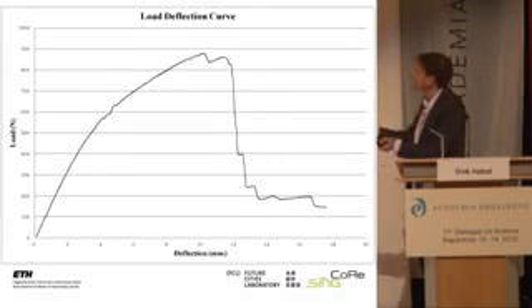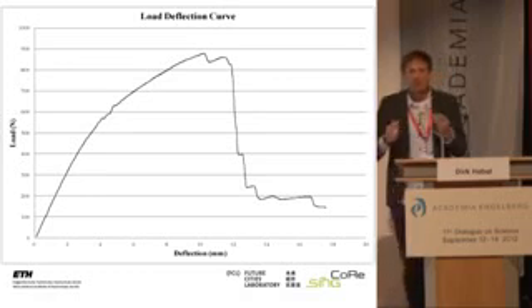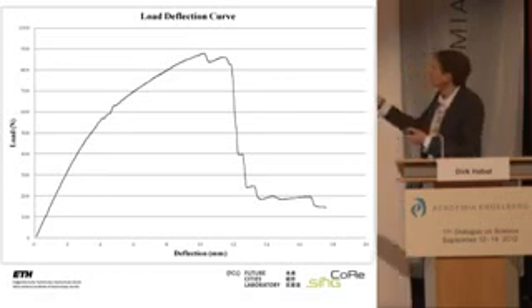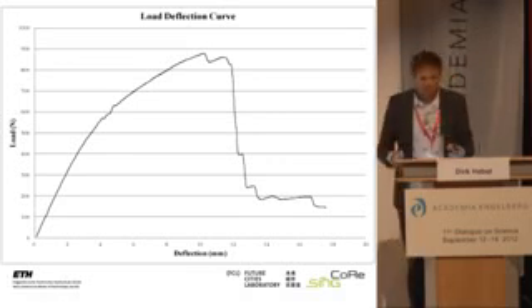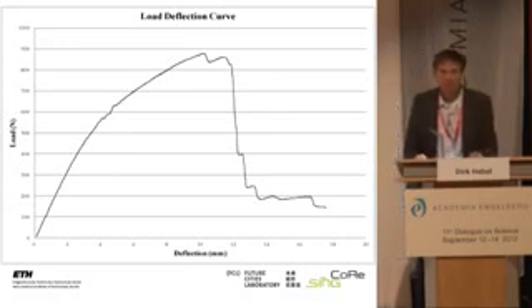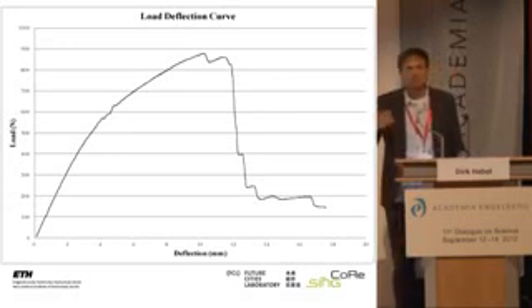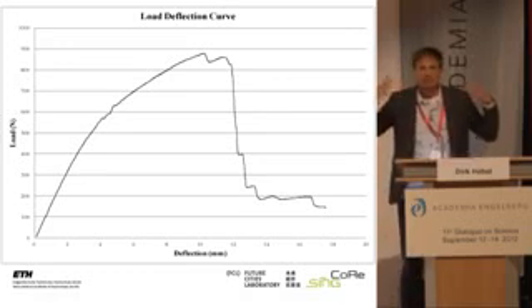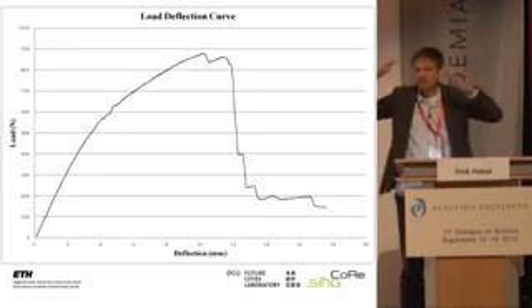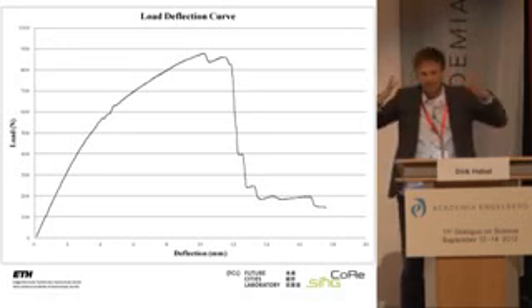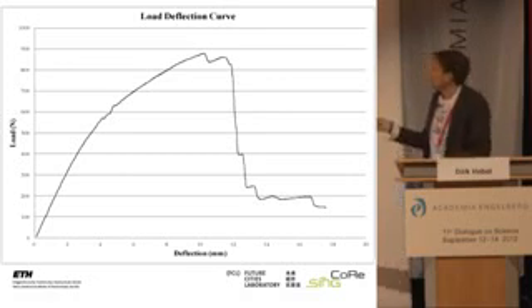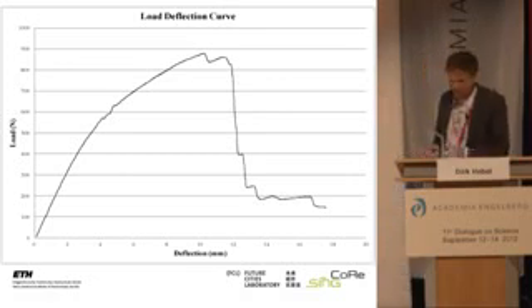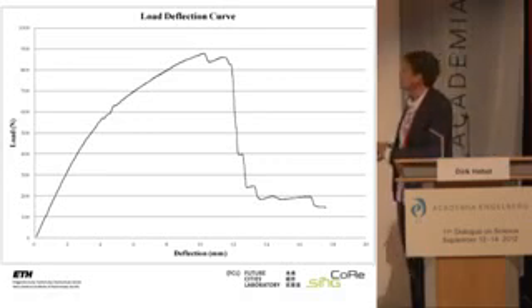Here you see the graphs of that again, so you have the first failure, again it picks up, similar to steel. So steel has the same capacity. In the first moment it starts to decrease the capacity and then picks up again, which is very important when you think about structures or concrete structures exposed to fire. So what we want is that our structures are not failing or collapsing in a second or in a moment, but that we have some time, even so the structures are deforming, giving still time for people to evacuate. And these results are very hopeful for us that the bamboo material has the same capacity.